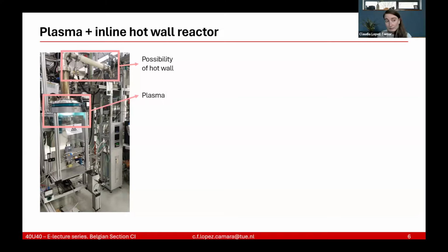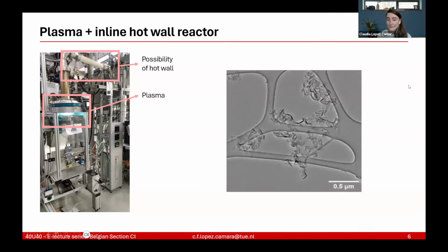And doing these plasma reactions, we can, for example, obtain graphene. So this is a sample of graphene that we created using the microwave plasma reactor. And it is this very crumbled material. The material that you see very plain and very structured is actually part of the TEM holder for the sample, and the sheet, let's say, of very crumbled material, that's actually the graphene that we get from the plasma reactor.